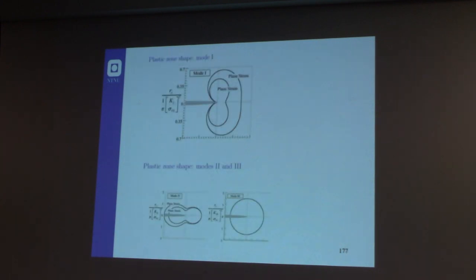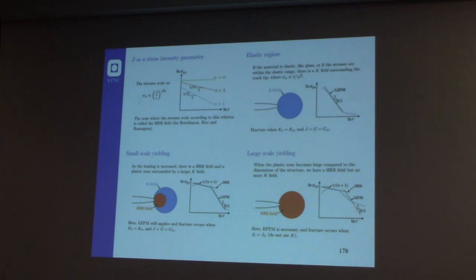Of course, the shape of the plastic zone depends on the mode that you are applying. For mode 1, you have a butterfly shape, but if you have mode 2, you have something like an 8 shape, and if you have mode 3, it is a perfectly circular shape.